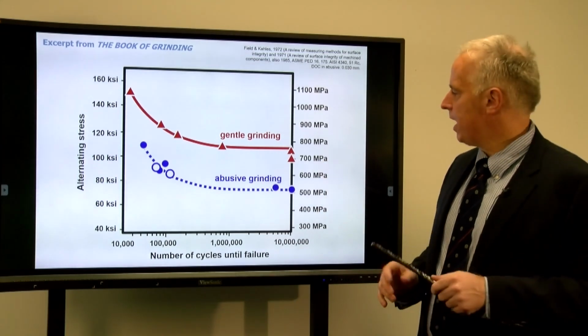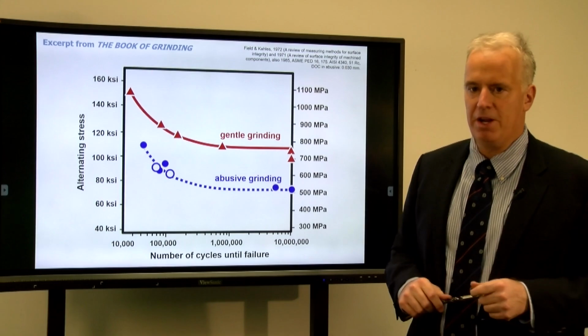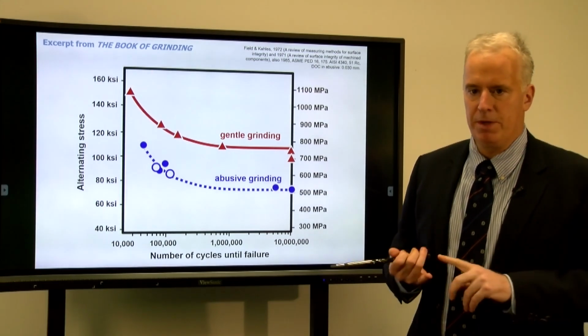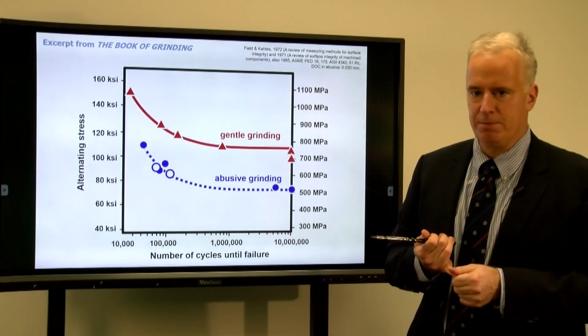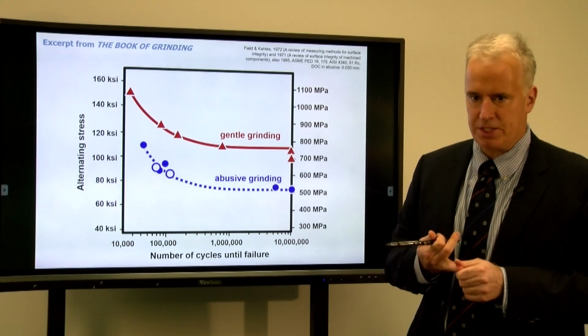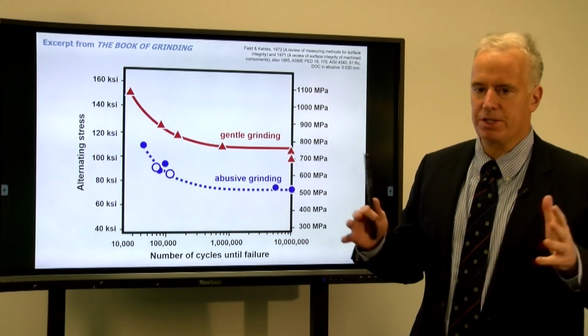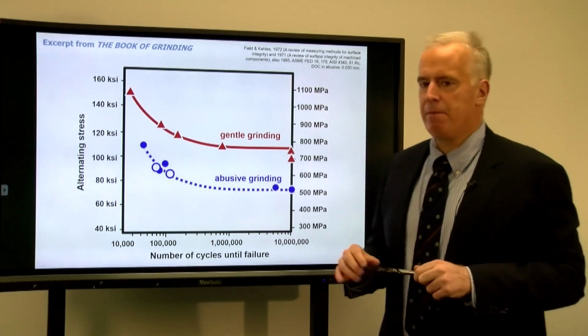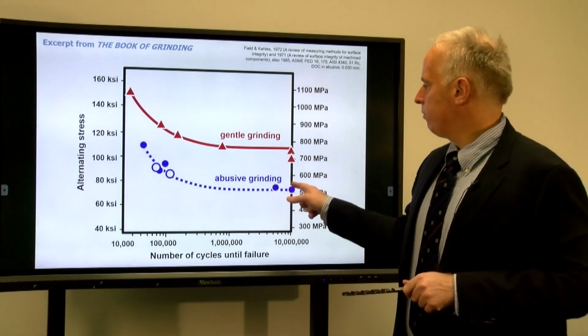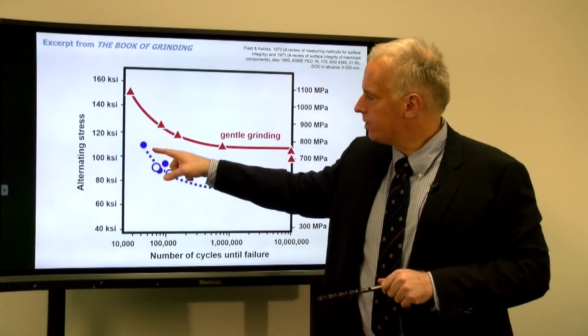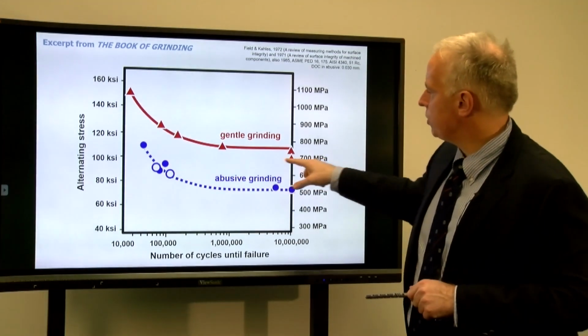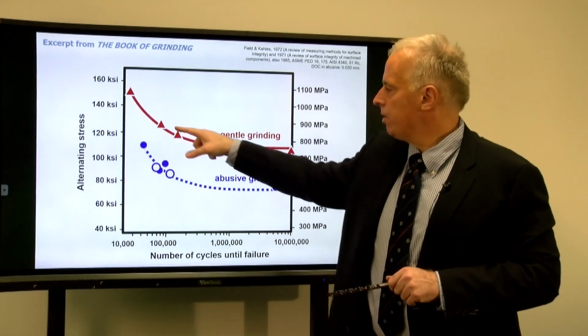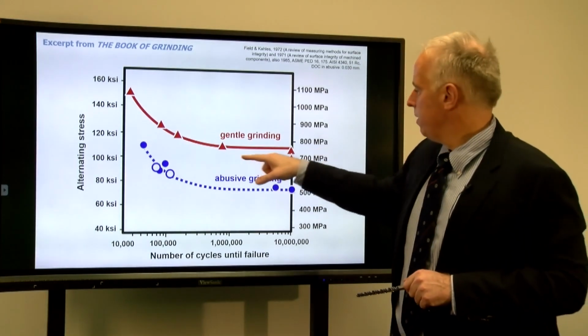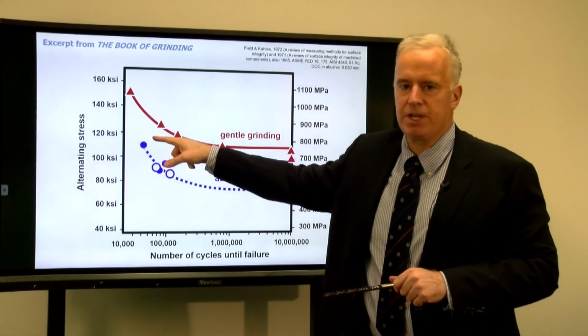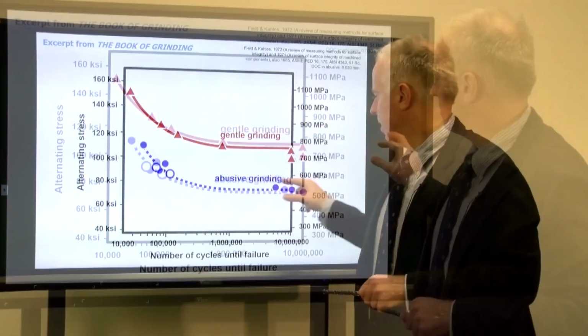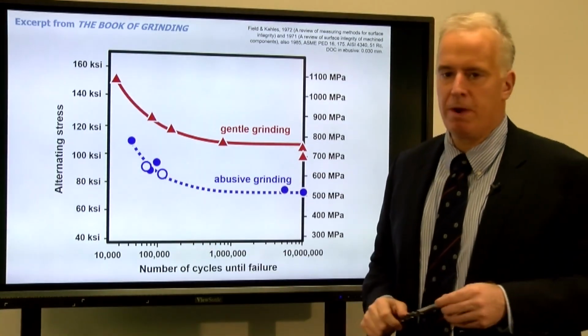But if we grind this guy abusively, and it depends on how you define abusively, we'll talk about that in a minute, abusively can mean we have thermal softening, the workpiece becomes soft, we have residual tensile stresses, or we have rehardening burn, all things that occur at high temperatures, and they damage the integrity of the steel. But if we have abusive grinding, now look at this curve, we get a shift. So if we apply just 700 megapascals, where if we don't abusively grind the guy, you can pretty much go forever, now we're only going to get about 30,000 cycles before he breaks. And if we apply 600 megapascals, we're going to get only about 100,000.